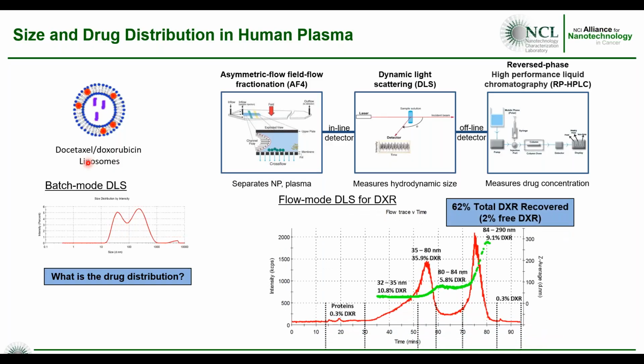So these are the results for the flow mode DLS for doxorubicin. Basically, the intensity of the light scattering is a function of time. And what we've done here is with the DLS, sizes are given here, shown in green. We can see we have varying different sizes or size populations in the sample. And by collecting each of these fractions, we can quantitate the amount of drug associated with that size fraction. So for example, you see most of the drug is contained in the size between 35 to 80 nanometers. I should also point out that AF4 in this case can separate out the nanoparticle from the free plasma proteins. What's interesting here though is we're only seeing 62% of the total drug recovered, with about 2% free, and this is done offline with another type of analysis.